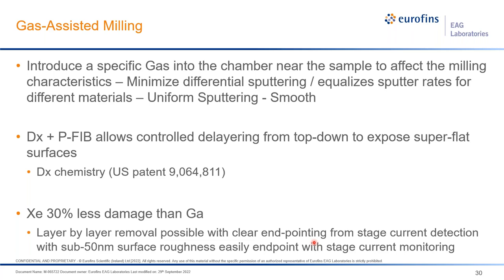So we can do this very controlled delayering and then document each of these layers with the SEM and then do reconstructions in the long run. So DX plus PFIB allows for this controlled delayering. And then we're going to use PFIB because it provides us 30% less damage than gallium, right? So we have a much more surface sensitivity. So the two combined together really give you the most optimal ability for getting the depth resolution that's required for these kinds of structures.